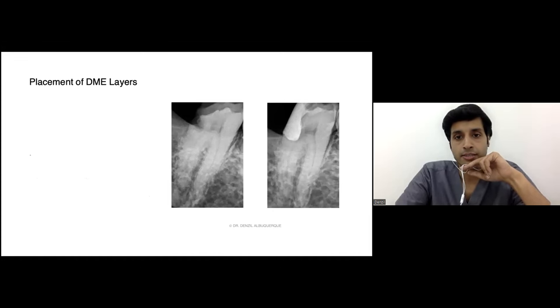Pretty much the same principles as root caries: the caries removal, and then IDS, that is immediate dentin sealing, and resin coat. But we do it in a maximum vertical height of 1.5 to 2 millimeters, in multiple layers of 0.5 to 1. And if you want to be as textbook as required, we avoid any contact with the axial wall. So we only want to build the height of the tooth without touching the axial wall.